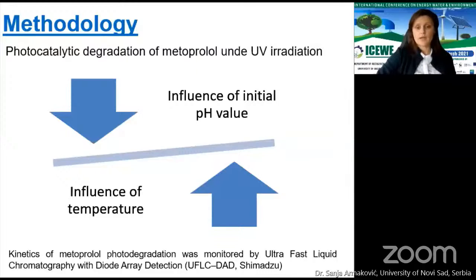The effects of the temperature and the initial pH value were studied. The initial metoprolol concentration was 0.05 millimolar, and the catalyst loading was 1 milligram per milliliter. For the kinetic study of metoprolol, we used liquid chromatography with a DAD detector, and aliquots of half a milliliter were taken from the reaction mixture at the beginning of the experiment and at regular time intervals. The suspensions were filtered through Millipore membranes.